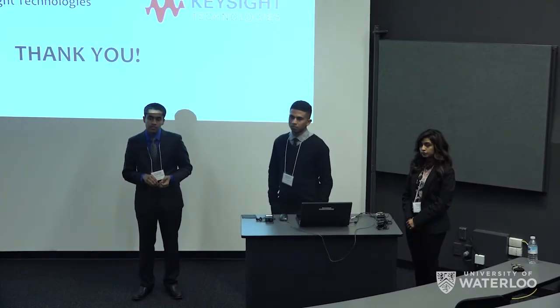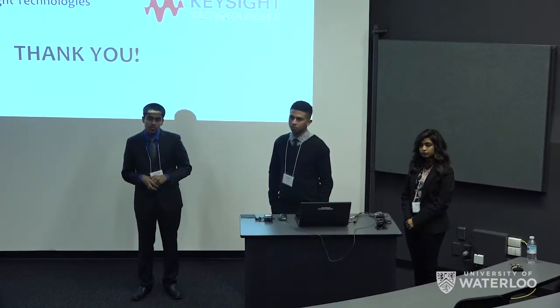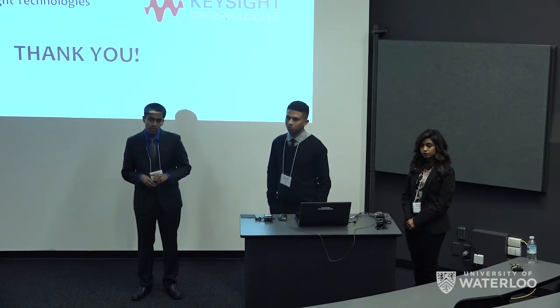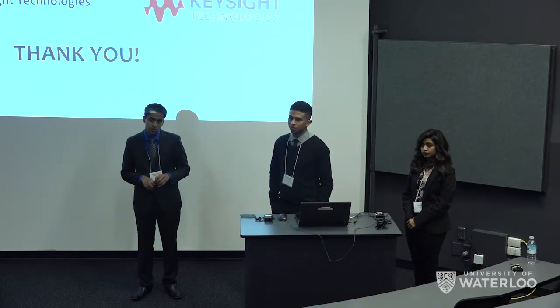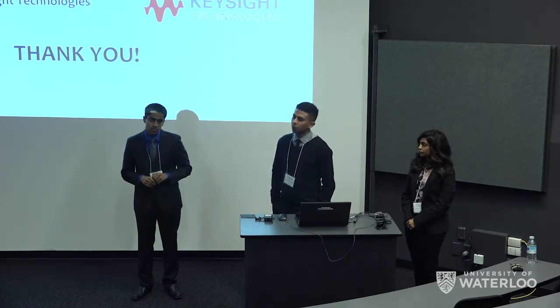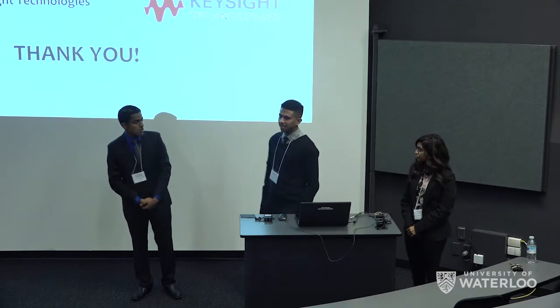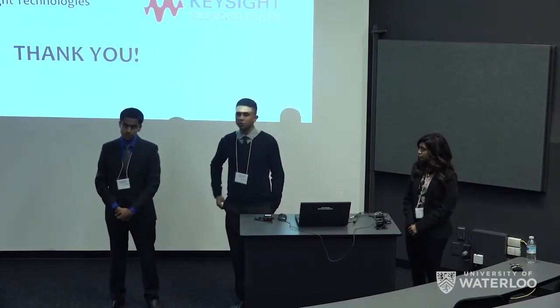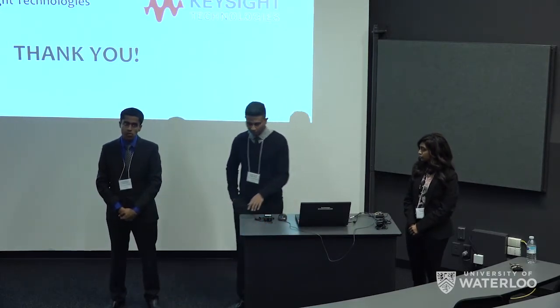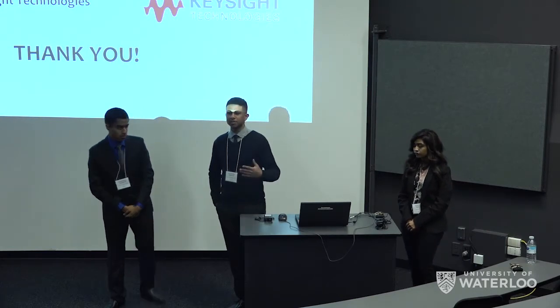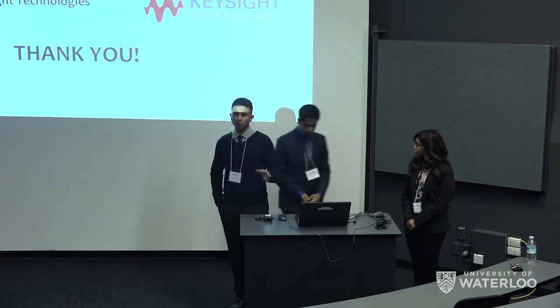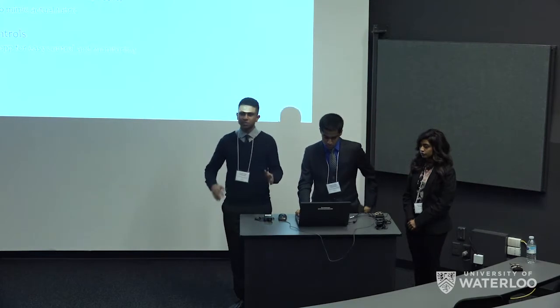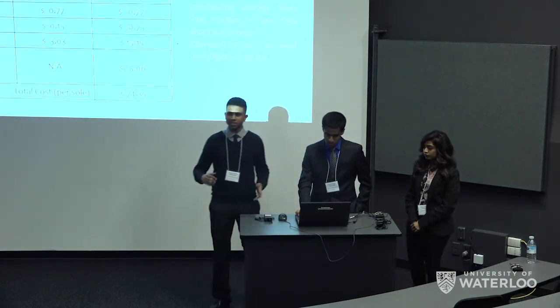I have a question. We have 1 minute. So what about reproducibility? Is there any evidence of sample degradation or curve modification as you take something, heat it for an hour, bring it back down? And how could we use this over extended periods of time, have you had a chance to evaluate that? So we haven't had a chance to evaluate that quantitatively very much, but we have noticed that once you're reaching high temperatures, because of the increasing conductivity, we're seeing a lot more current travel through. So it's definitely an issue in how we're looking at the regulation.